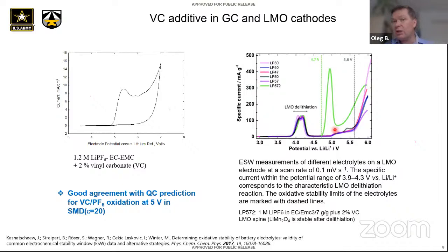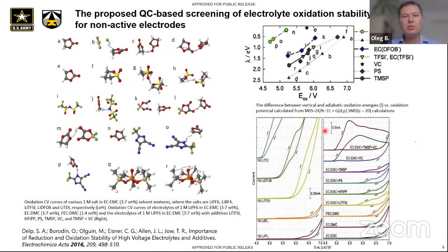So that seems like a nice unified picture, and that's what we try to apply for screening and understanding of behavior of different electrolytes at oxidation, on non-active electrodes. So for example, in this case, we took solvents like EC with various anions. And let's start with the EC with TFSI. I'm plotting here calculated results. Lambda is an approximation using a vertical minus adiabatic difference, right? So that's all the deformations occurring during oxidation step. And N and P are these points.